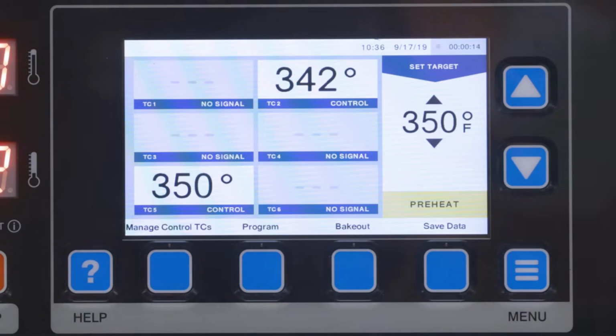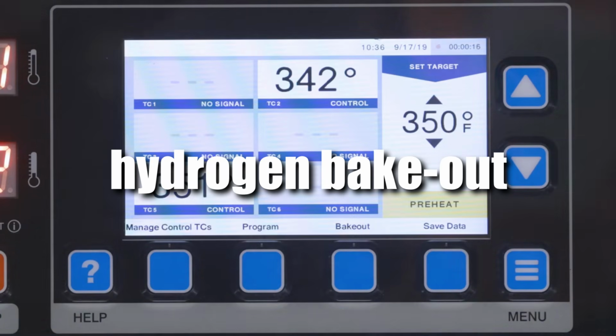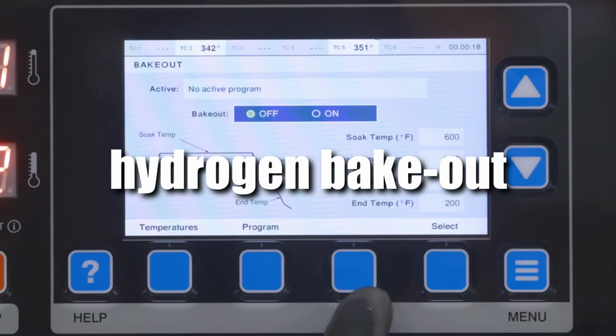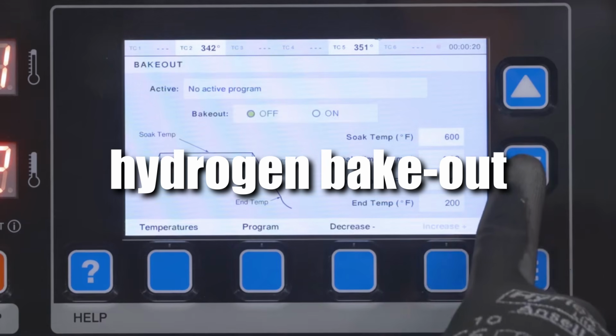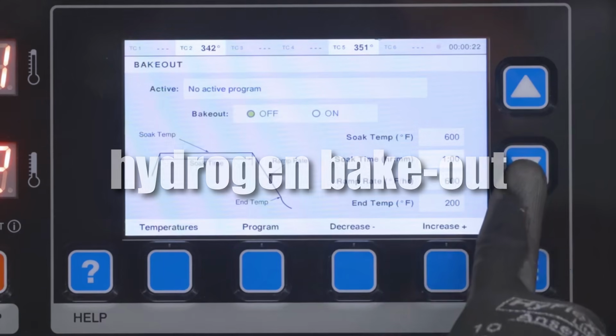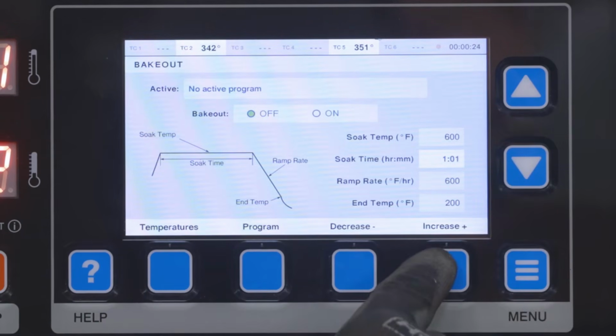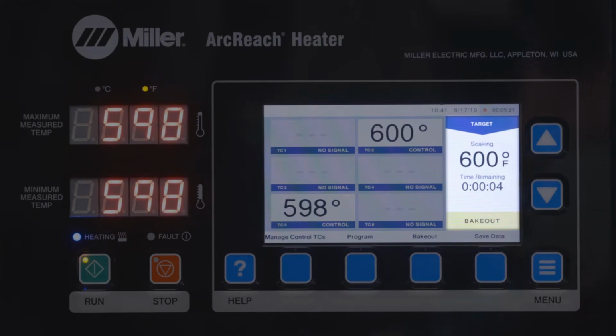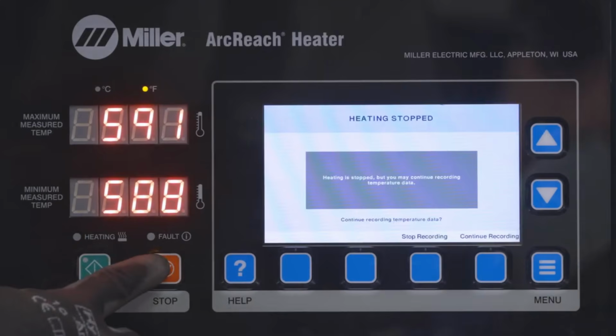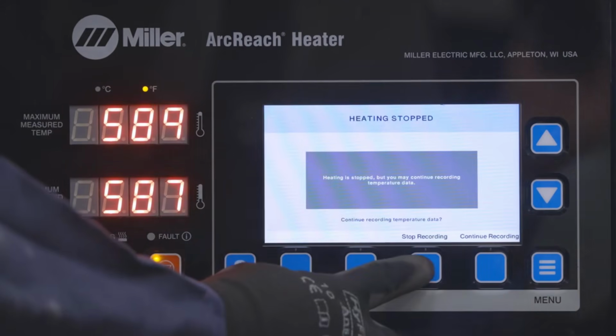The industrial fix is a process called hydrogen bakeout, heating the affected steel to between 375 and 430 degrees Fahrenheit for a minimum of 1 hour per inch of material thickness. That drives the trapped hydrogen out of the lattice before it causes permanent microcracking. You are not doing that in your garage. The correct solution is to never introduce the problem in the first place.